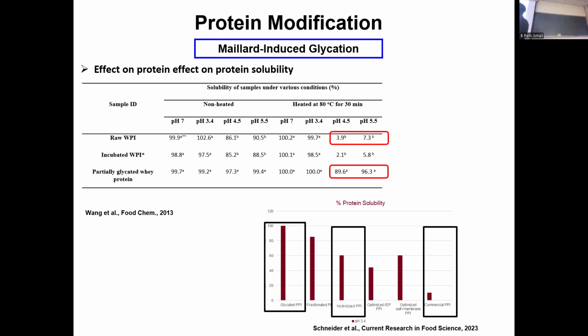But the most important discovery was we don't have to go to pH 3.4. We can formulate at pH 4.5. It's still acidic. You can still do the mild pasteurization. The regular whey protein denatures when you heat it, right? Remember, if you heat it, it denatures. So at the isoelectric point, it's going to fall out of solution. But the glycated protein remained soluble at the isoelectric point. So that was great. We can formulate a beverage at 4.5, and we did. You pasteurize it like it's an acidic beverage, and then it stays soluble.